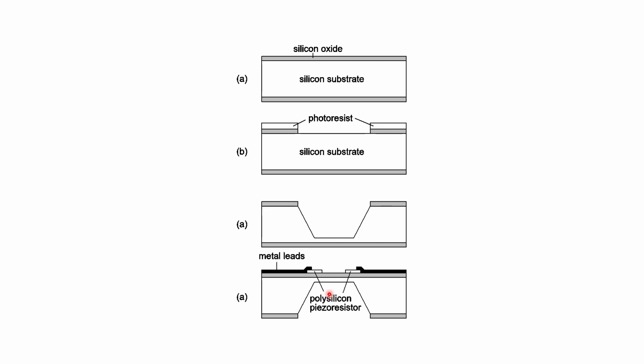If you have a process where the result is very much determined by the timing, then you don't have a robust process. In this case, if the etch rate is fixed and you etch a little bit further, then the membrane thickness would change. And that would be not ideal for a pressure sensor device. So only use this as an example.